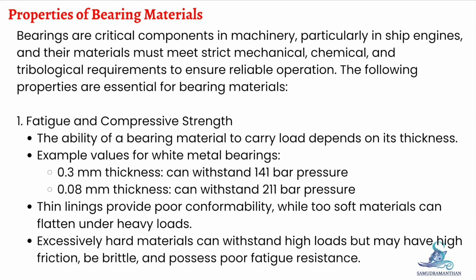First, we have fatigue and compressive strength. The ability of a bearing material to carry a load depends largely on its thickness. For example, a white metal bearing of 0.3 millimeters thickness can withstand about 141 bar pressure, while a thinner 0.08 millimeters lining can handle 211 bar. But here's the catch: thin linings have poor conformability, and too soft a material can flatten under heavy loads. On the other hand, overly hard material can take high loads, but tends to have high friction, brittleness, and poor